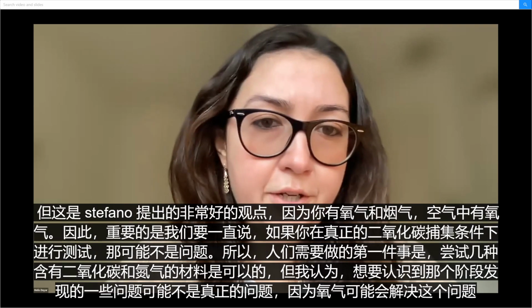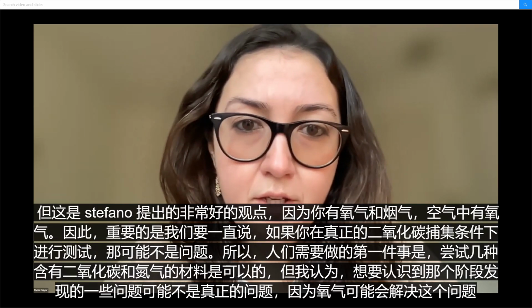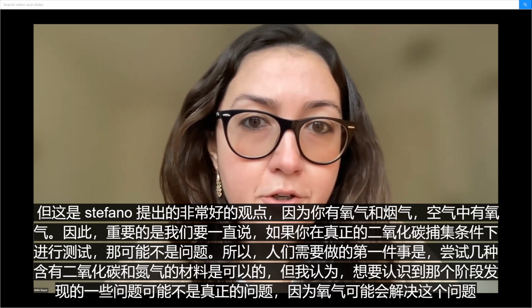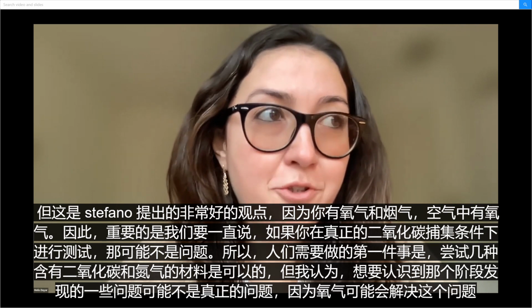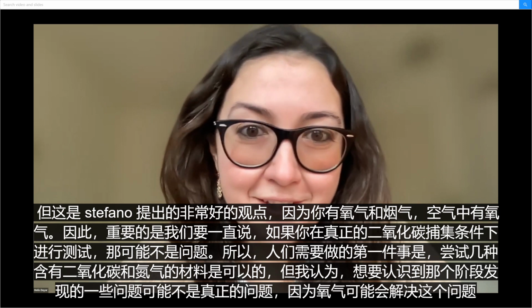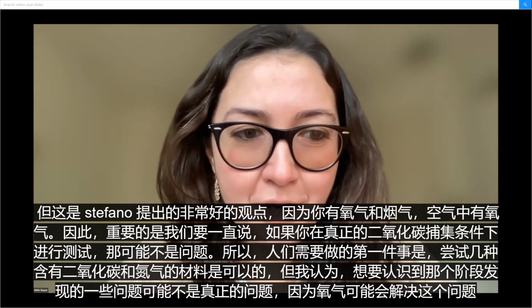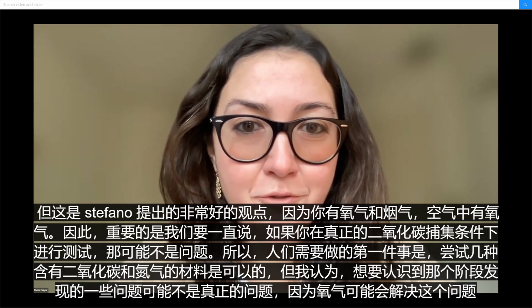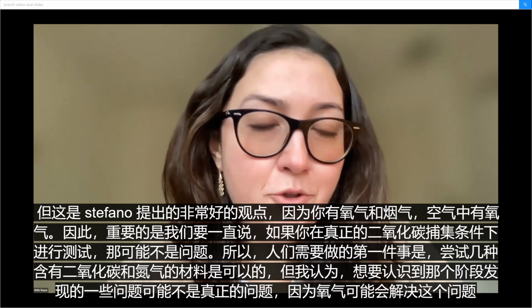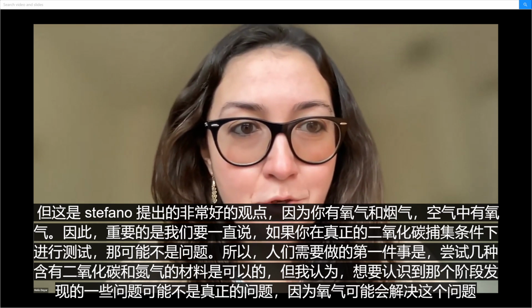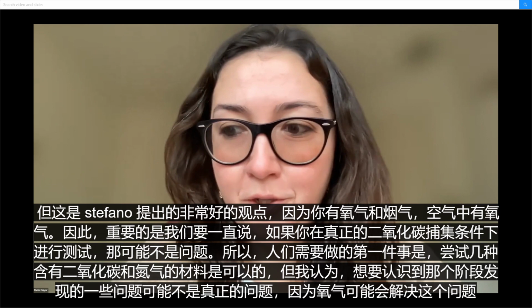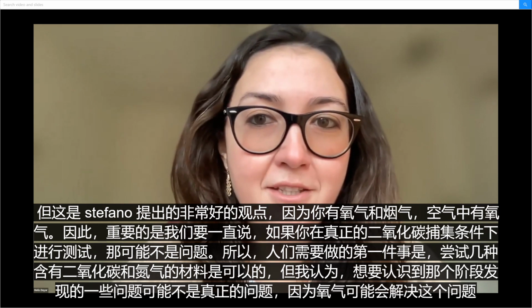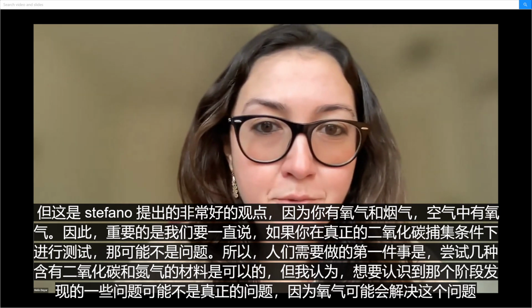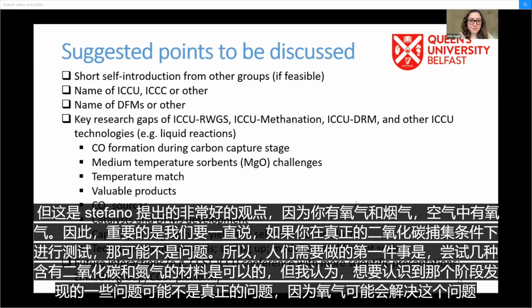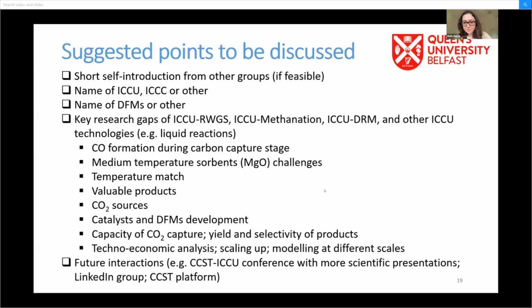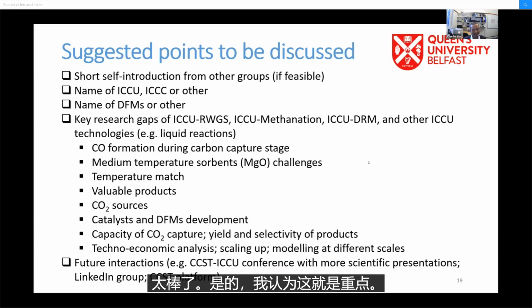But that's a really great point that Stefano was making, because you have oxygen in flue gas and you have oxygen in air. So it's really important, and we keep saying this, that if you test it under real CO2 capture conditions, that might not be a problem. It's okay to try out a few materials with CO2 and nitrogen, but I think one thing to recognize is that some of the problems identified at that stage might not be real problems, because the oxygen might take care of it already. That's great, I think that's a good point.